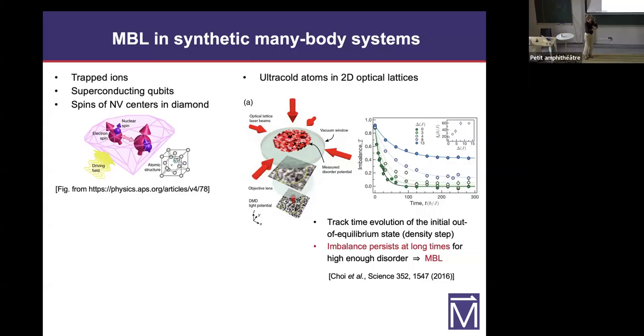So what they did, they prepared this 2D lattice, and at time equals 0, they can remove the atoms from one side of their system. And then they can measure the difference in the density between left and right sides as a function of time. So they measured the imbalance between the two sides as a function of time, and they were also able to vary the disorder. In the case of 0 disorder, which corresponds to these green symbols, you can see that this imbalance drops rapidly to 0. In other words, the density becomes uniform very rapidly. But as you increase the disorder, you can see that this imbalance persists for a long time, and this was taken as evidence of many-body localization.